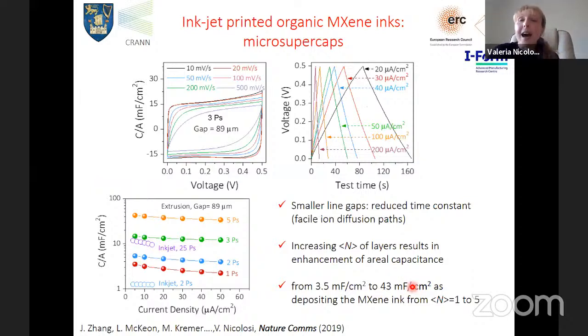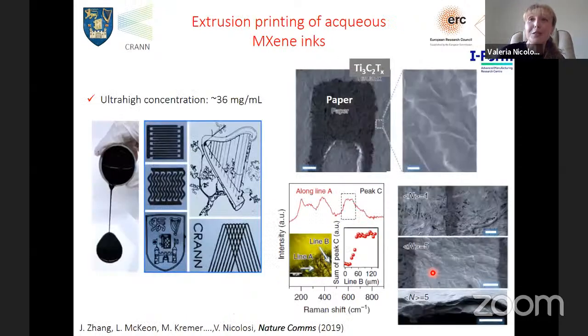What we could see was that indeed these devices worked wonderfully as supercaps. Here is the areal capacitance of devices with only 3 layers printed, and with a gap between the fingers in our interdigitated material of 89 microns. And we could push up to 500 millivolts per second, and indeed very nicely capacitive behavior. Here is how the areal capacitance performs with current density for different deposition passes, basically. So we could go from a one deposited layer device of about 3.5 millifarads per centimeter square up to 43 millifarads per centimeter square with only 5 passes, which was really well performing. We were very happy with this result.